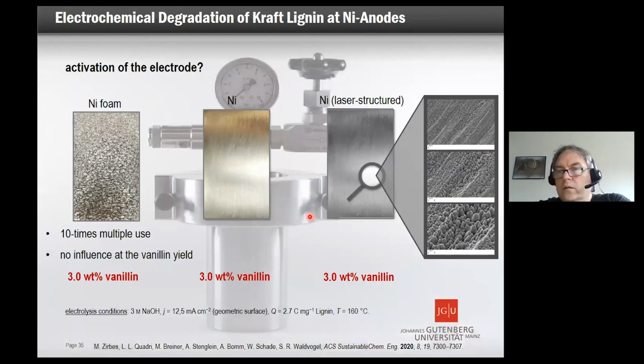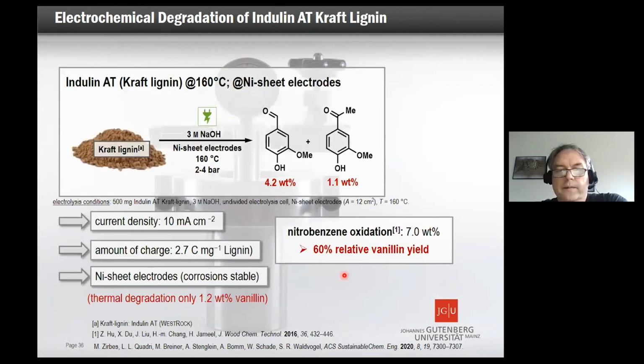And it turned out we do not need foam anymore, because at 160 degrees, the kinetics are so fast. Therefore, you can even work with planar electrodes, which makes it much easier to install. Therefore, it's the same yield. Even if you have a planar system which is laser crafted, it ends up with the same yield. Therefore, it has not much influence anymore.